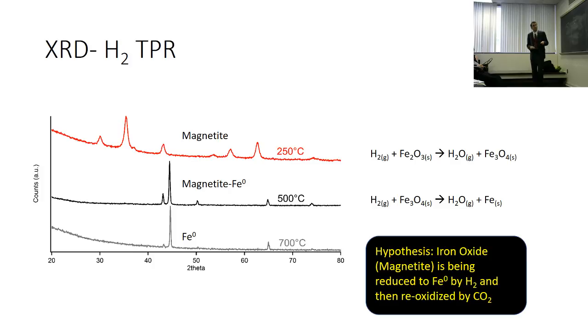Magnetite does do reverse water-gas shift. So it seems like you have to go to magnetite first, and then you have this switching maybe that's occurring between magnetite and iron. If you look at 500, it becomes a mixture of iron and magnetite, so it seems like it's a balance between reducing with hydrogen and reoxidizing with CO2.